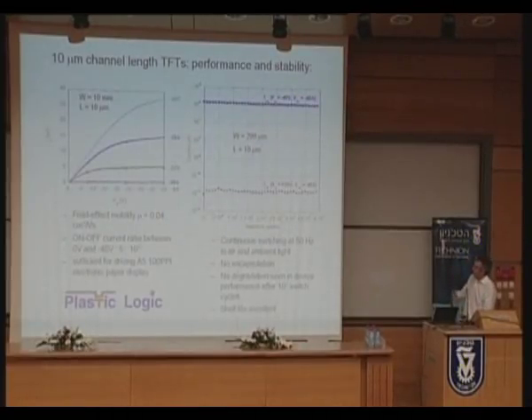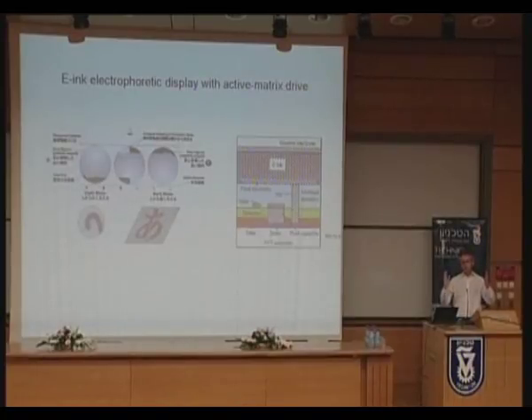What is here is, if you like, the sort of sales pitch as to what can be done now. There is an organic polymer used in place of silicon. It has the figure of merit, the field effect mobility, for this particular example, a factor of 10 down on amorphous silicon, so it's not great. But these are transistors working in moist air, so they don't need encapsulation. And they were made at room temperature, which you can't do with silicon. And they have pretty good on-off ratios, 10 to the 5, something like that. And they're good enough to provide an active matrix backplane of transistors to switch a display.